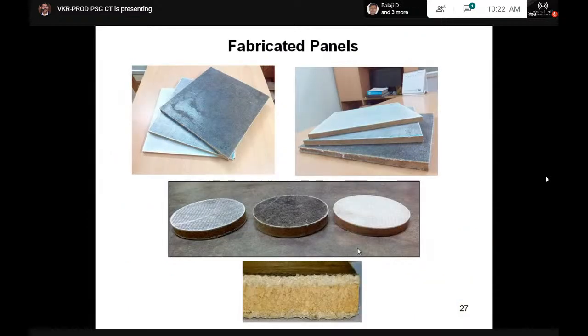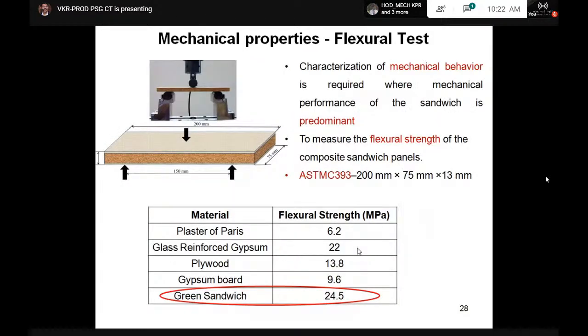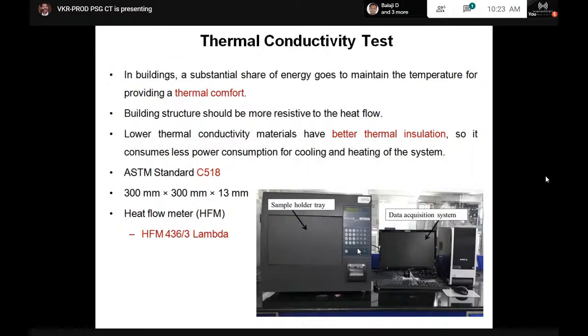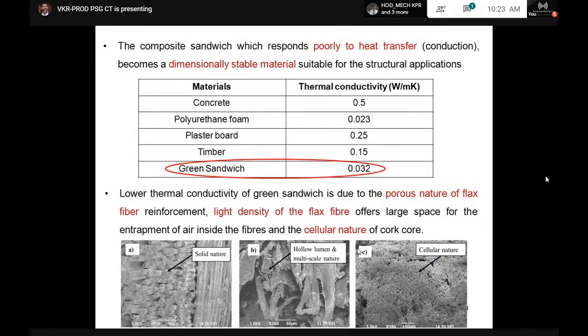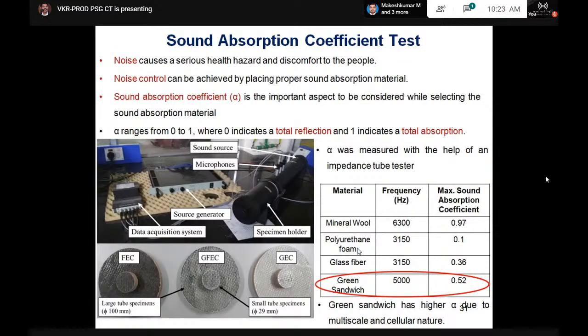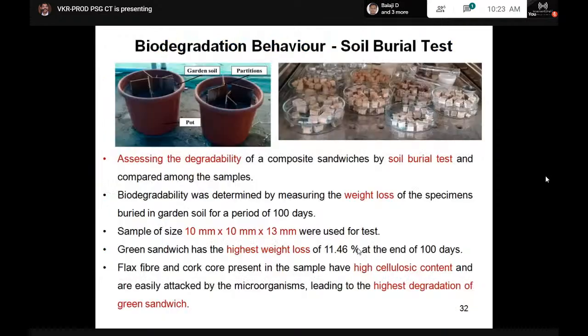We made a lot of specimens, mainly for characterizing the sandwich panels, and we found that the flexural strength is much better than its counterpart, maybe the material which we try to replace, like plywood or gypsum board or glass reinforced gypsum. So we got better strength. And thermal conductivity tests were also conducted, and we found that the green sandwich has a thermal conductivity of 0.032, that will help. Another property which we can appreciate is the sound absorption coefficient test, where the green sandwich has a coefficient of 0.5. So this is what we have done.